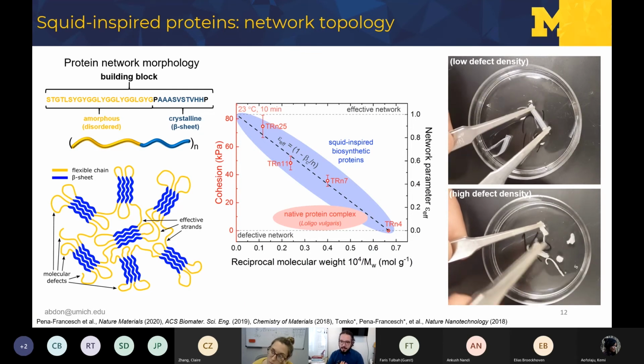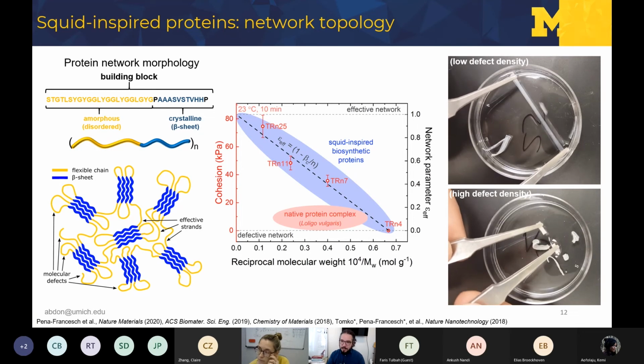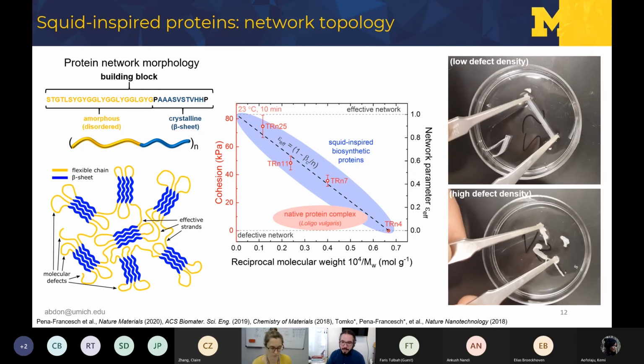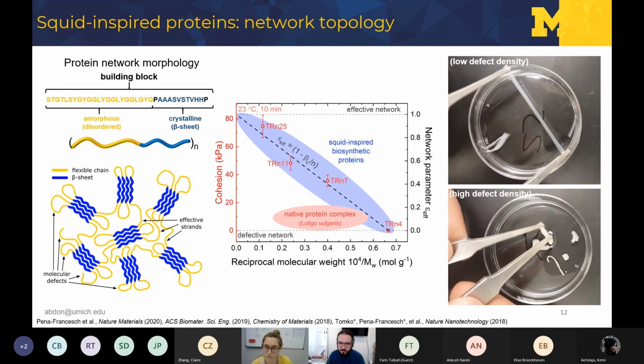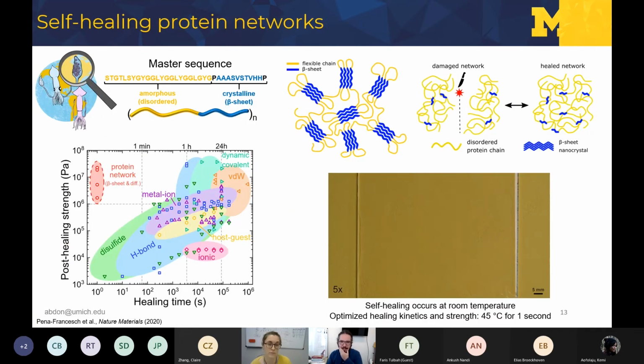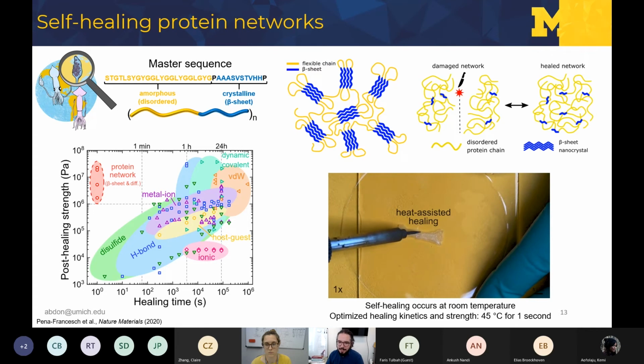So once we had this optimized network with optimized mechanical properties, we looked into the healing properties, right? And basically, now that we have a good network without defects, can we repair that network through the beta sheet formation? And you can see here that it's quite fast, right? In this case, we give it a little bit of temperature, around 40 to 45 degrees. We can heal within seconds, right?